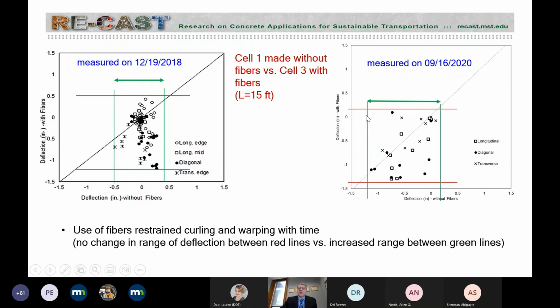So the difference between the horizontal lines did not change much, but the difference between the vertical lines changed a little bit. So we can conclude from that is that the use of fibers seems to restrain curling and warping in the long run. And then there's no change in the range of deflection between the red line. Yeah, this is what it means.